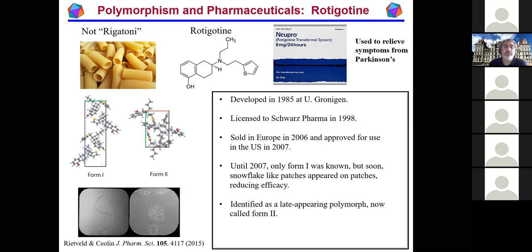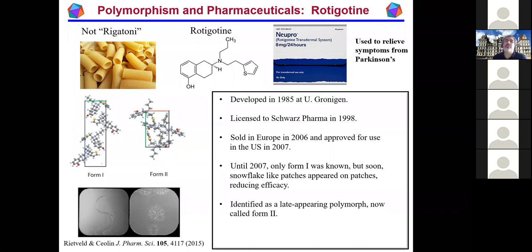It's called a late-appearing polymorph because you don't see it when you make Form 1, all right? So this is predicted by Ostwald's rule, which says that the least stable forms of a crystal will be the ones that form first, and then the most stable forms will form after that.